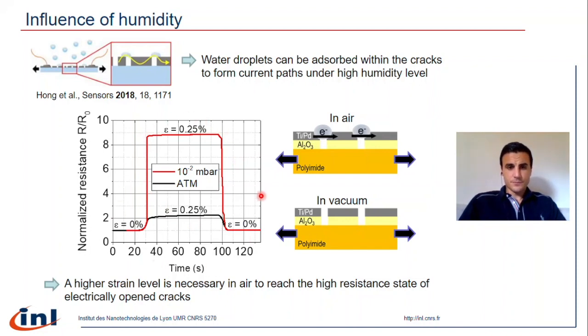As you can see, the resistance variation is 4 times higher in vacuum than in air, which confirms that a higher strain level is necessary to break this water droplet path to reach the high resistance state of electrically open cracks. These results possibly confirm that shielding the cracks with a photoresist layer can avoid the effect of humidity on the electromechanical response.